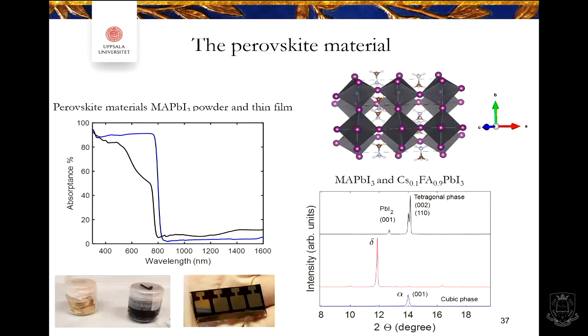I can just say that this is a comparison of what you usually see in absorbance. This is a classical thin film of perovskite, and here is the homogeneously grown material band gap. Like was just mentioned, tetragonal phase, cubic phase, FAPbI3 for instance, cubic alpha phase. But when you work with FA, you also have to be careful because at lower temperature it creates this delta phase instead. So then you have to look for the delta phase. Delta phase is yellow, still a crystalline structure, but with a much broader band gap.